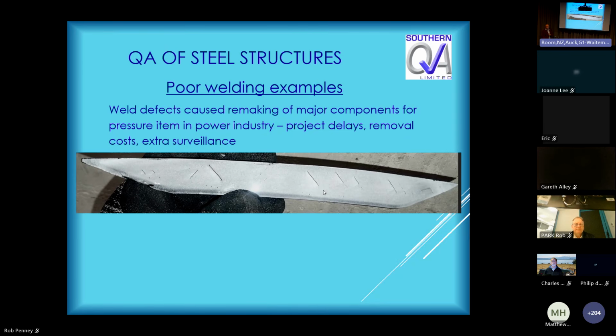It's very unusual, but it was a major issue. And there could have been a number of contributing factors. And the most likely one is a very excessive heat input to the weld. But in this case, this was a pressure item for the power industry, and it had to be completely remade. It was made in China, and this is what was found after it arrived in New Zealand and was installed. So they had to uninstall it. The last time I saw parts of this item, it was on the back of a truck heading to the scrap metal dealer in Christchurch, and I just happened to drive the other way.